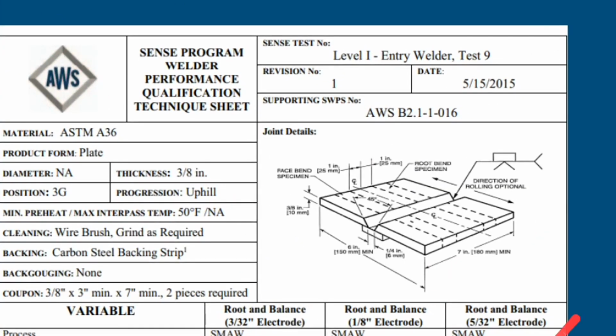So here's the vertical sheet, similar thing. Again, we're doing a 22.5 degree bevel on each side. We've spec'd out a 1/4 inch root opening, and it's going to be a progression of uphill. That means we have to start at the bottom and work our way up. I wish they would change this diagram and have it standing up on our page, but they have it laying down. But yes, you do need to work from the bottom up. You cannot run vertical down on this particular WPS or this particular test that we run.